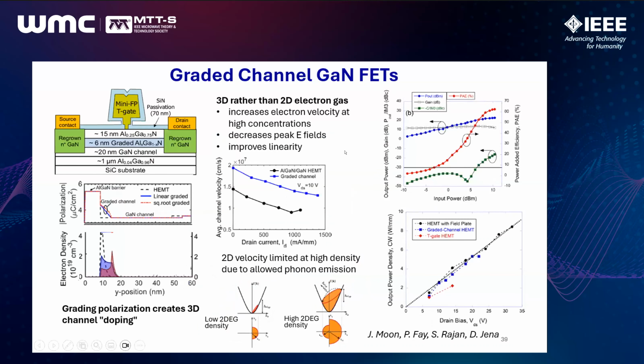As a final note, I'd like to discuss the graded channel gallium nitride work that has been emerging, and it's associated with the fact that the aluminum gallium nitride is graded for a 10% range over a distance of 6 nanometers, instead of having the usual abrupt junction in the barrier and the channel. And in this case, the polarization charge leads to essentially a 3D electron gas instead of the usual 2D electron gas. And this succeeds in increasing the electron velocity, which tends to saturate at very high current densities for the case of the 2D electron gas. It allows the velocity to be increased within the devices.